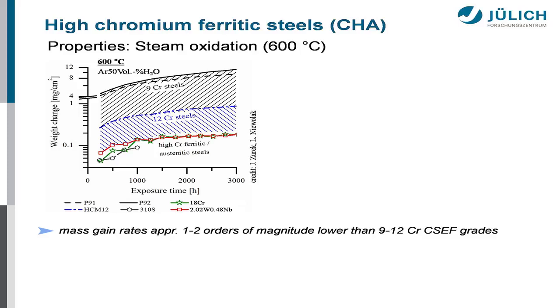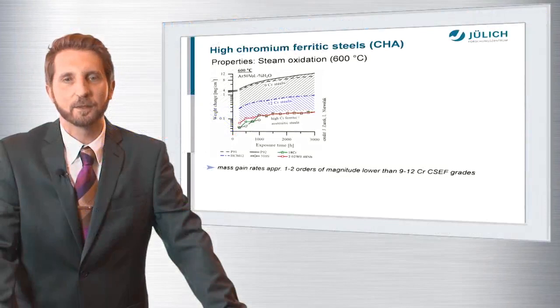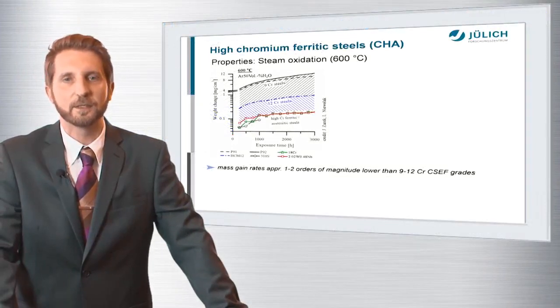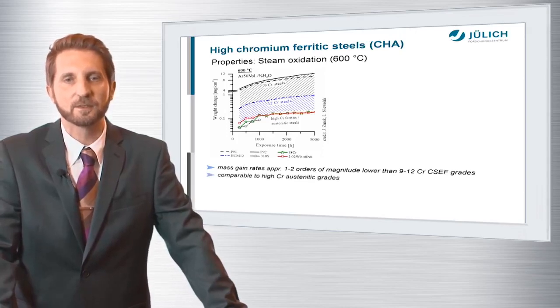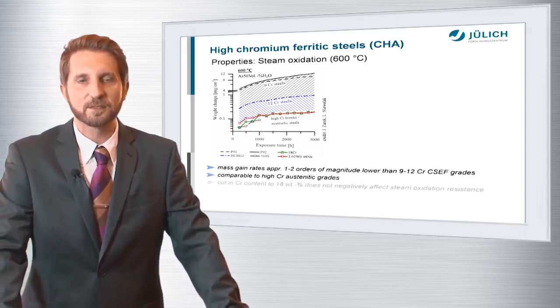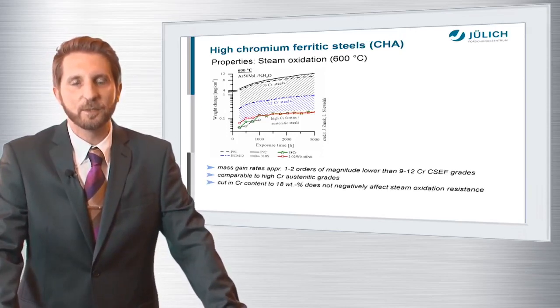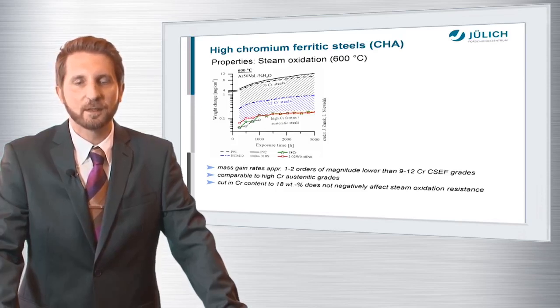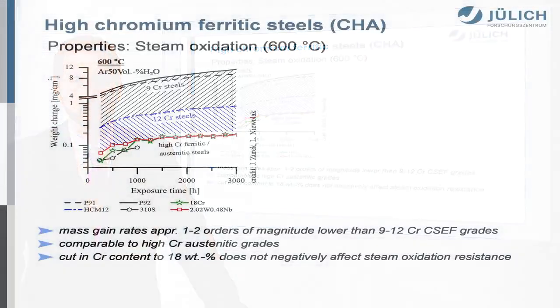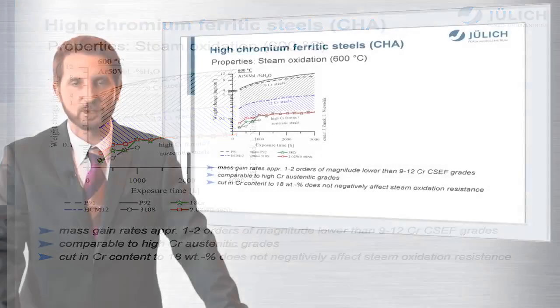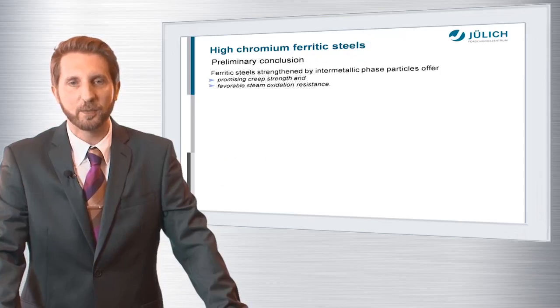You see on the upper end you do have the performance of the 9 chromium martensitic steels, approximately an order of magnitude lower the performance of the 12 chromium steels, and approximately another order of magnitude lower at the lower end of the 12 chromium martensitic steels. We do have the weight gain rates of our high chromium ferritic steels, which is mostly comparable to high chromium austenitic grades. And what is really nicely depicted here is the comparison of the green 18 chromium curve and the red 22 chromium curve. You see that they more or less are on the same level, and that means that the cutback in chromium content to 18 weight% does not negatively affect steam oxidation resistance, which was one of the basic findings in the award-winning paper.